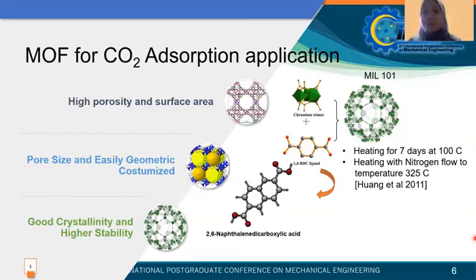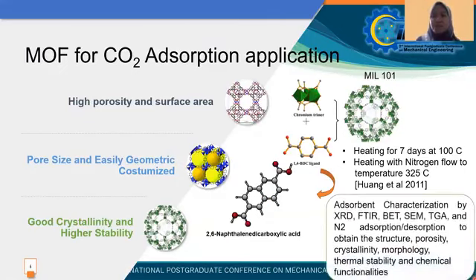Because MOF is very easily geometry customized, we would like to utilize the advantage of MOF by changing the ligand. We do the ligand functionalization by changing the 1,4 BDC ligand to 2,6 NDC ligand. As you can see the difference between these ligands, with this double ring of benzene, we hope that CO2 molecules will be captured more, because the new MOF, MIL-101 NDC, has high surface area and pore volume. And after we do the synthesis of MIL-101 NDC, we do adsorbent characterization by some techniques.